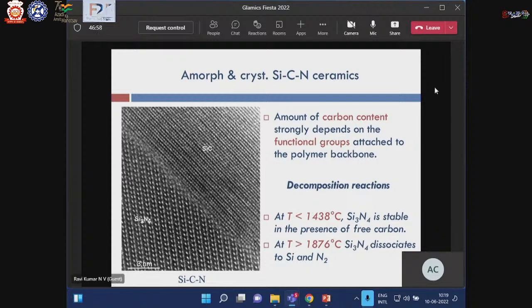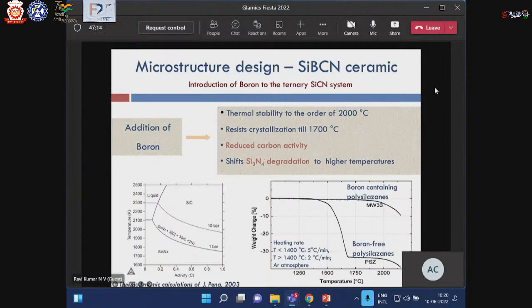So that is a problem, because such a nanocomposite will start degrading in the presence of carbon beyond around 1500 degrees Celsius. And of course, you cannot use them beyond 1800 degrees Celsius because silicon nitride itself starts dissociating into silicon and nitrogen. So one of the strategies, more than 20 years back, was to introduce boron into the silicon carbon nitrogen system, basically to reduce the carbon activity. And it was shown that once you start introducing boron, you can make these materials highly stable till around 2000 degrees Celsius without any degradation.